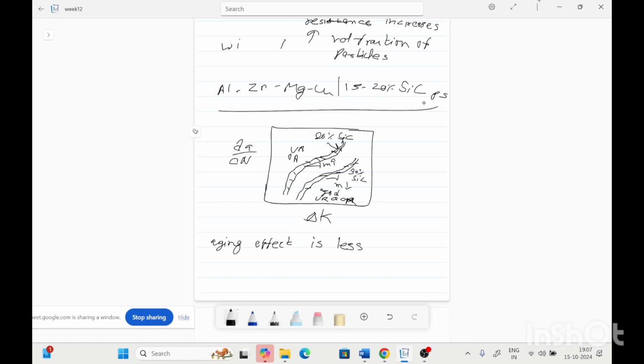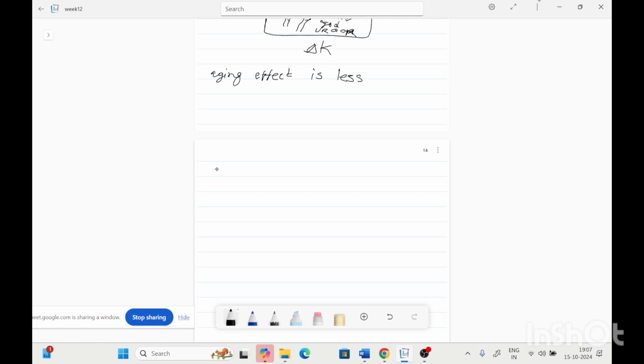The increase in particle volume fraction decreases the crack growth rate, while for the aluminium 3.5 copper matrix with the silicon carbide reinforcement, so this composite, the effect of volume fraction is less on the crack growth rate. Means volume fraction is less effective in reducing crack growth.